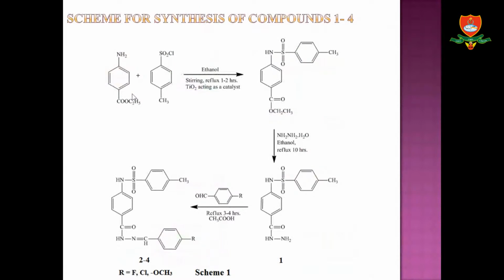This is a synthesis of a compound. This is the scheme for the synthesis of compounds 1 to 4. First, ethyl aminobenzoate is reacted with the sulfonyl chloride in ethanol medium in the presence of a small amount of titanium dioxide, and this mixture is stirred for 1 to 2 hours. After that, the product sulfonyl amide is formed.